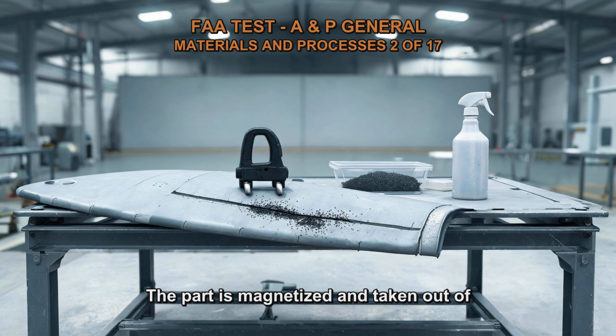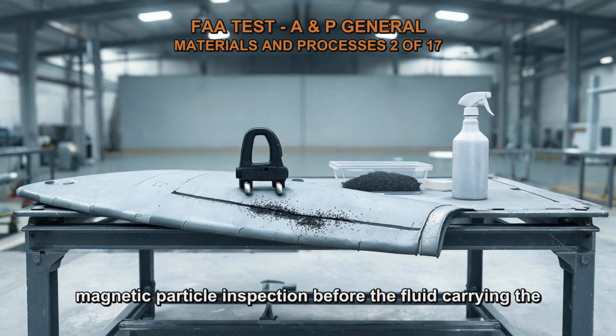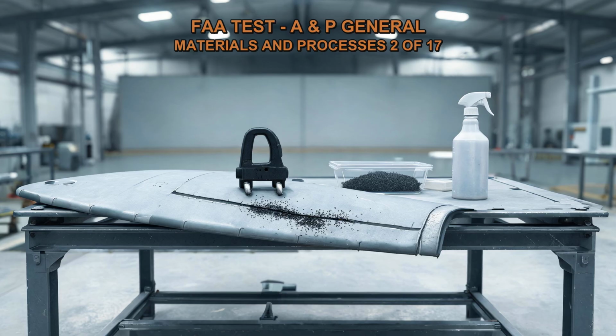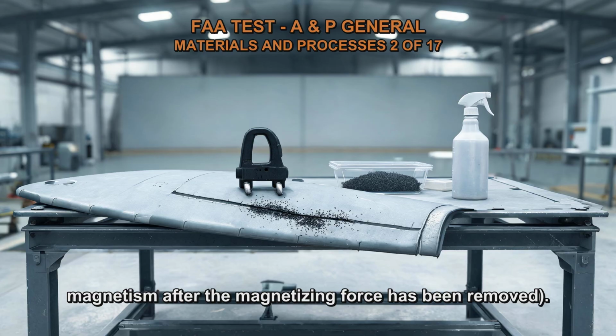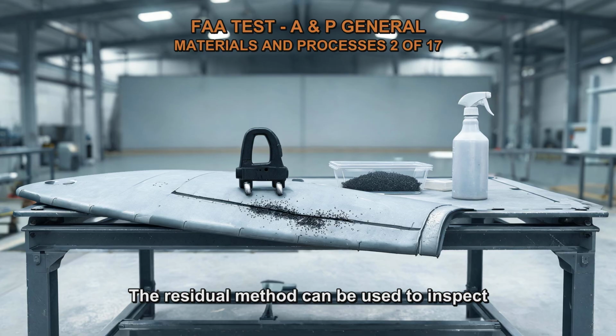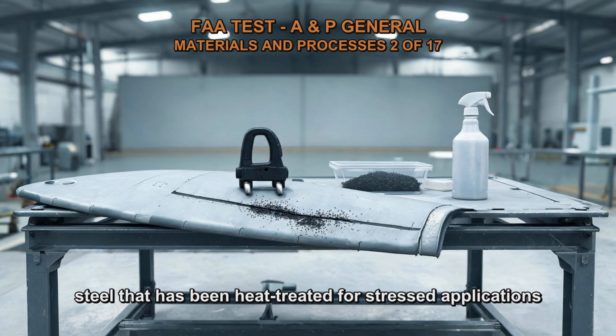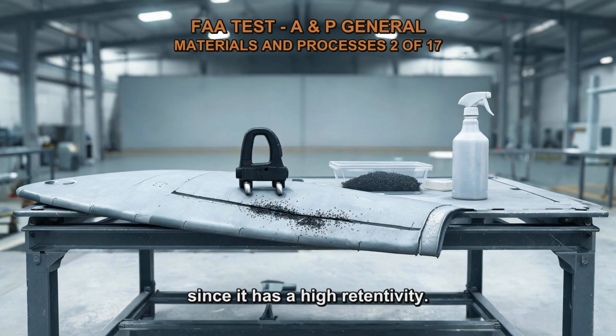In the residual method of magnetic particle inspection, the part is magnetized and taken out of the magnetic field before the fluid carrying the oxide is pushed over it. The residual method can be used to inspect steel that has a high retentivity, retains its magnetism after the magnetizing force has been removed. The residual method can be used to inspect steel that has been heat-treated for stressed applications since it has a high retentivity.